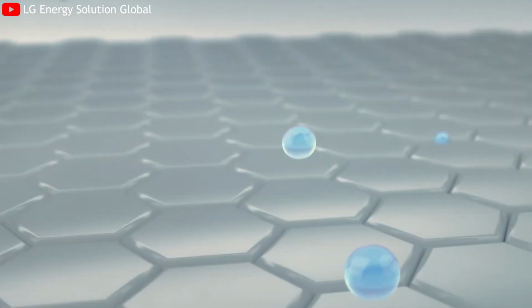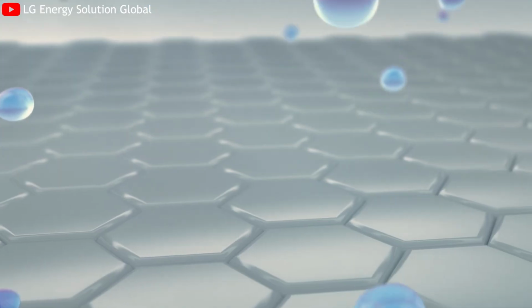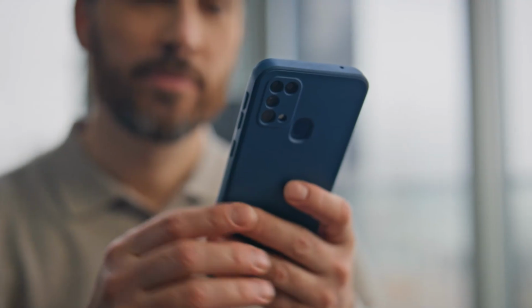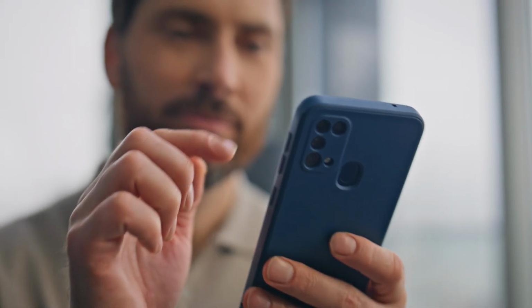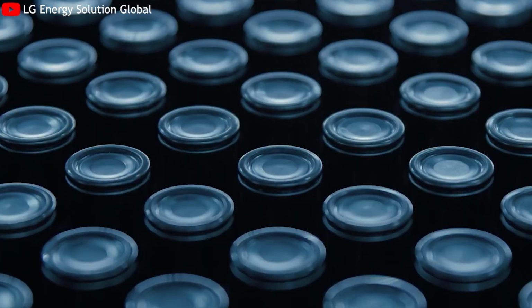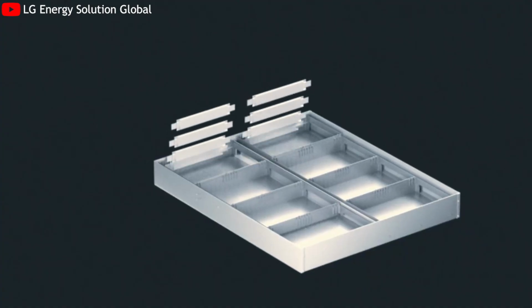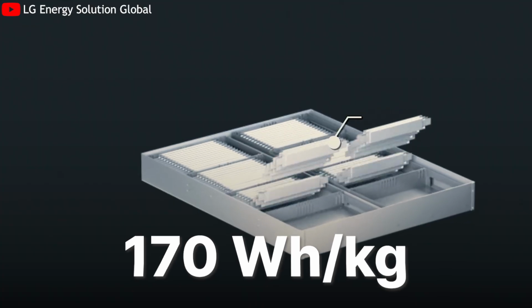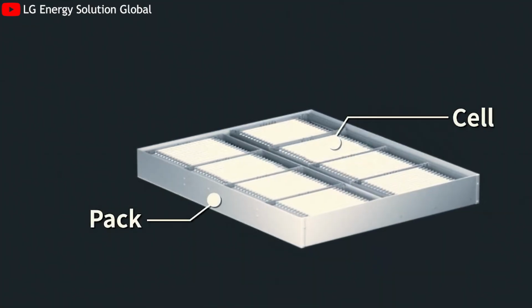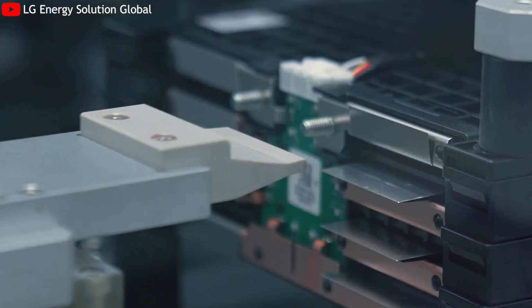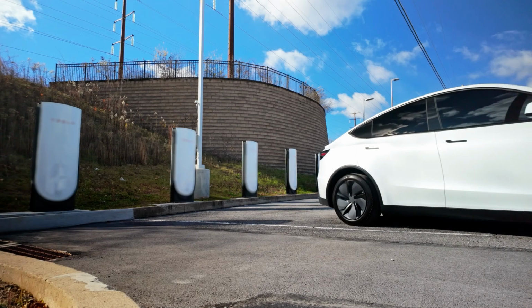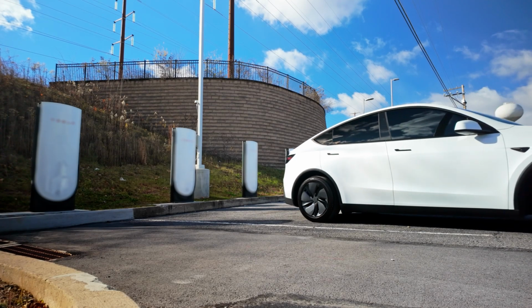The second constraint is energy density, and this one is not negotiable. The media loves quoting watt-hours per kilogram because it looks impressive. On that metric, advanced sodium-ion cells have reached 160 to 170 watt-hours per kilogram, close enough to LFP to create the illusion of parity. But vehicles are constrained by volume, not weight.